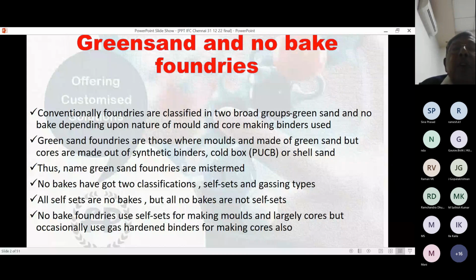In case of no bake foundries, the binders for mold making are no bakes. Not just no bakes, it is a special subdivision, a subclassification of no bake, that is self-sets. It means these are 2 or 3 component systems, all used with the sand, preferably in a continuous mixer, and the fluid sand is packed into the patterns called molds and cores, and these are stripped when these become hard.